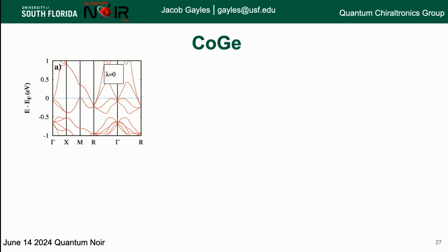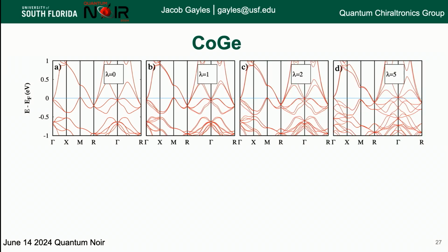So my postdoc and student did a bunch of calculations on this, and this is for what's called cobalt germanium. We looked at it without spin-orbit coupling, which reproduces the previous results. And then as we increase spin-orbit coupling, we produce those Weyl points, and we can see systematically here, this is the case for the experimental result, but as we systematically increase it, we keep those Weyl points throughout.